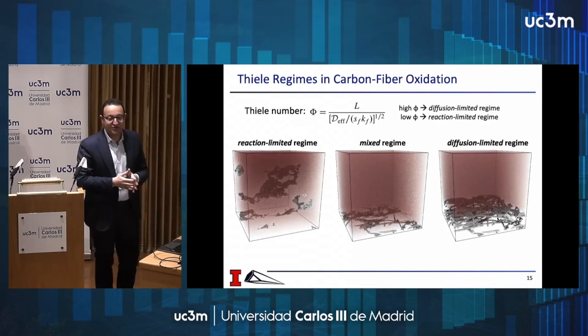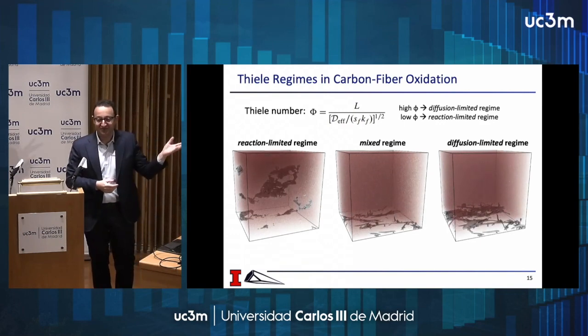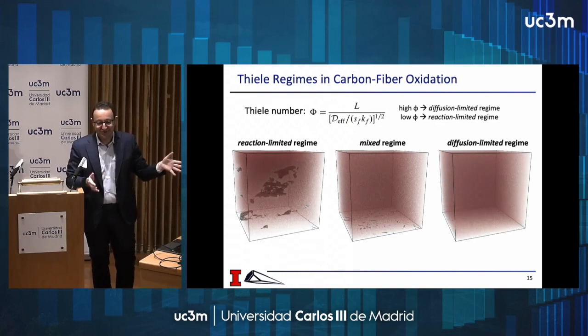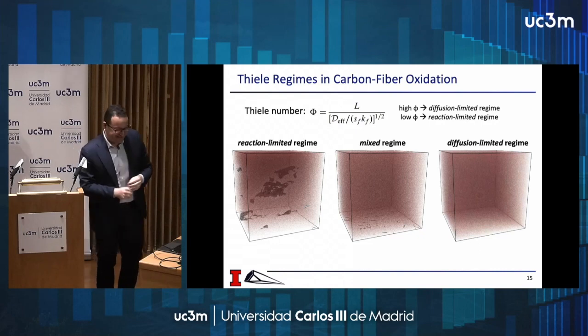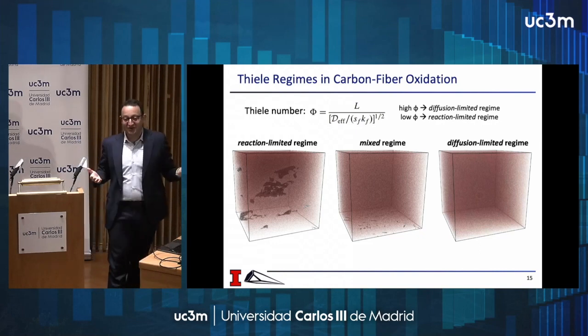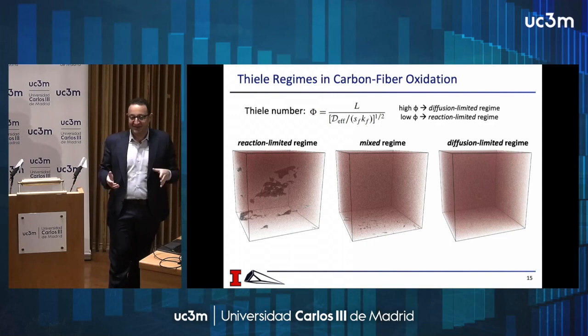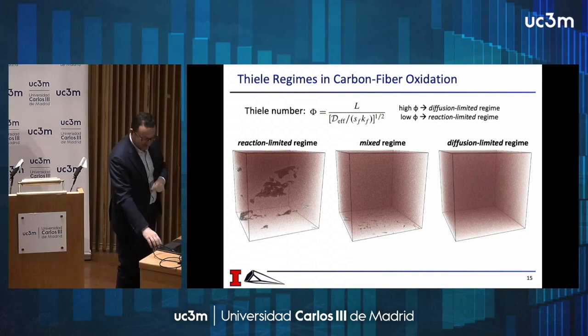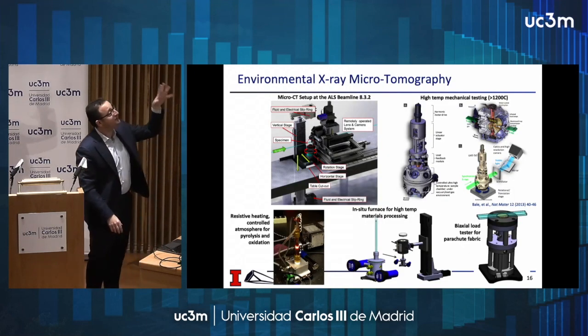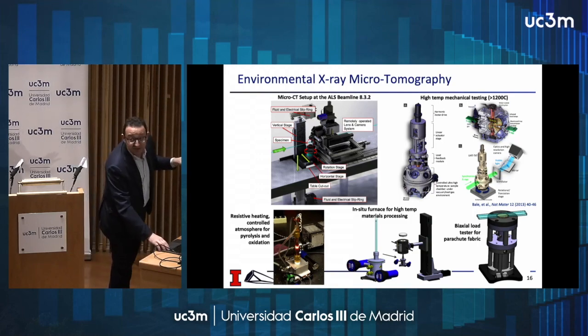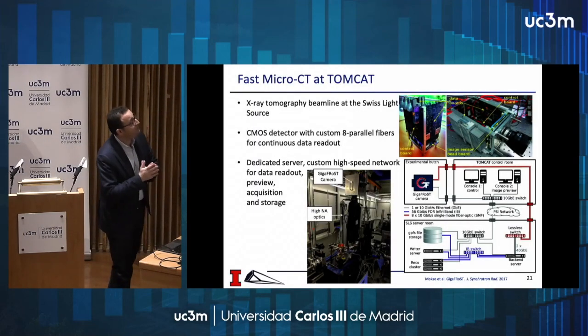Now what I'm going to show you is that it's possible to capture this experimentally, and it's something that we did about a year ago, and we're still busy processing some of the results. Of course, we are using X-rays again, but this time, instead of using X-rays on a static model, we use X-rays in a very fast setup that allows us to capture the dynamics of this decomposition problem. So we apply what is called environmental X-ray tomography. I'm going to skip over this because I'm short on time.